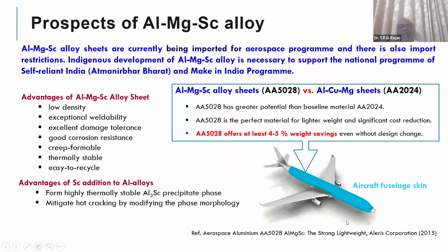So the next system is the aluminum-magnesium-scandium alloy. The advantage of aluminum-magnesium-scandium alloy is that scandium forms very fine precipitates of Al3Sc, and this Al3Sc is a highly thermally stable precipitate which enhances the properties of aluminum. Normally this alloy has very low density and very good weldability. When common aluminum alloys are welded, the strength will be around 180 MPa. But this alloy will have a weld strength of 230 to 280 MPa. That means structures will have better properties. It also has excellent damage tolerance, good corrosion resistance, creep formability, is thermally stable, and is easy to recycle.